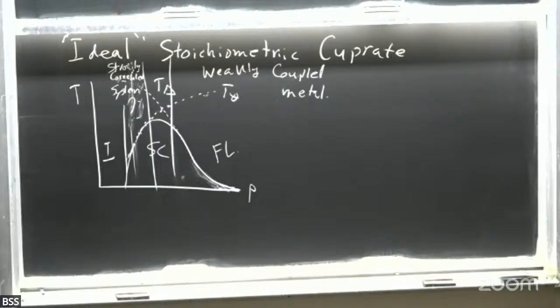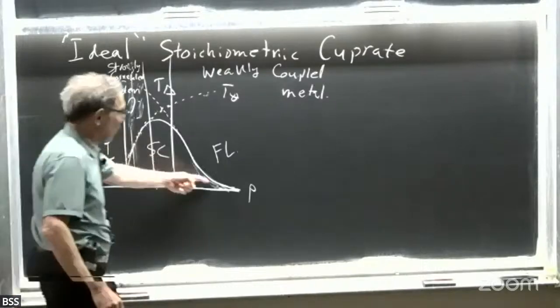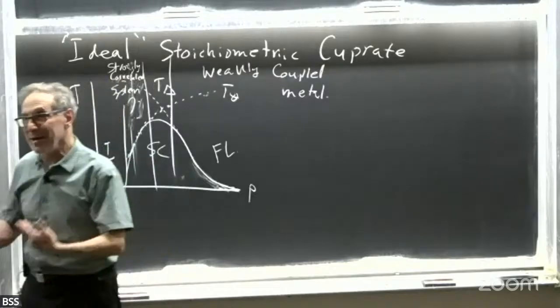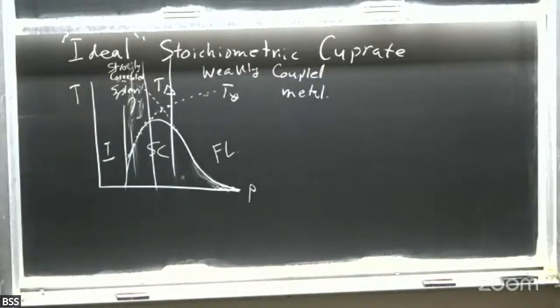You mentioned the Cambridge experiments that they measured. So you don't know what the doping is. If you plot Tc versus pressure, it looks like this. But translating pressure into doping requires other experiments. Yeah. So you said what you were saying? I would be a little bit careful about that. So even in the underdoped materials, when superconductivity is suppressed with high fields, they see quantum oscillations, and the quantum oscillations obey Lifshitz-Kosevich. So even there, at the end of the day, Fermi liquid, the last laugh.